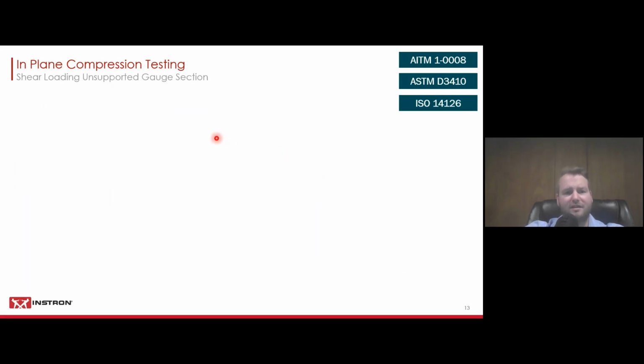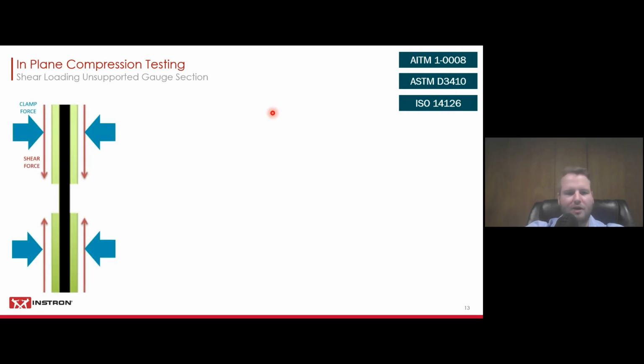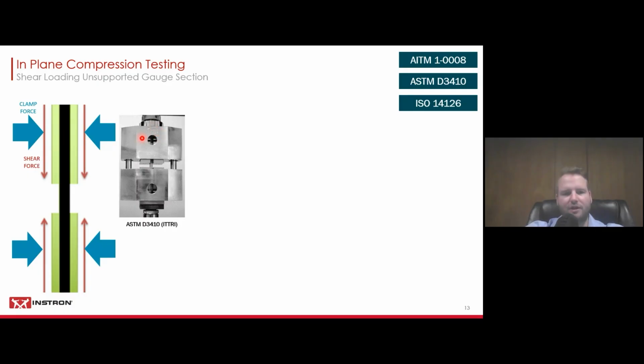Now we're going to move on to the next category, which is still in-plane compression testing, but now we're initiating the force into the specimen with shear. The most common standard here is the ASTM D3410 and also ISO 14126, and there are also a couple of other standards from Airbus, for example, that run compression like this. So now the difference is you're using tabbed specimens typically, and then you initiate the force from the side. So you clamp onto your specimen with a test fixture, something like the Illinois Institute of Technology Research Institute (IITRI) fixture that you can see here from ASTM D3410, and also allowed in ISO 14126.